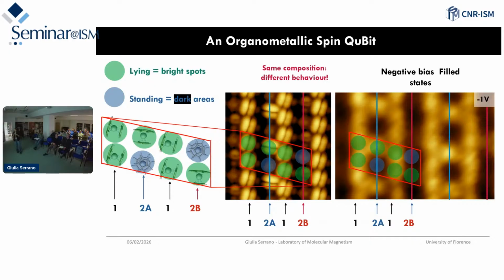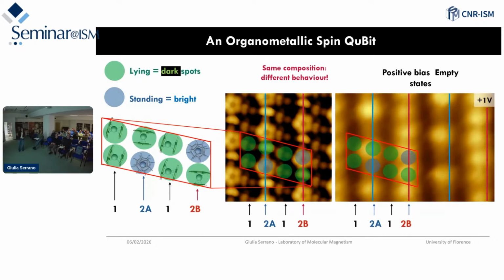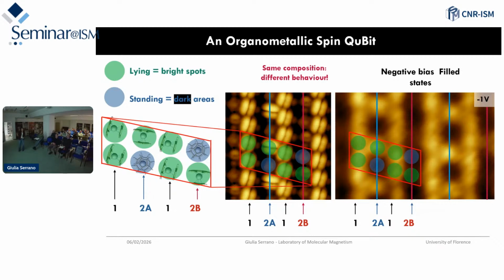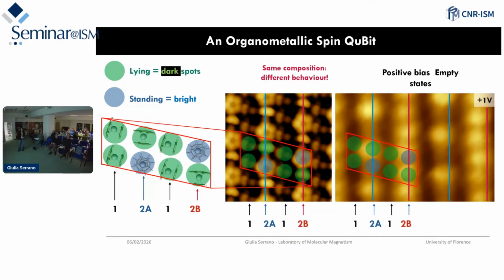So the rationalization of all of this came when we considered the packed layer. In the packed layer, we had a combination of standing, blue ones, and lying molecules, and we could rationalize this quite puzzling STM pattern by DFT simulation, and these are the real images, in which the pattern was actually rationalized by this quite complex cell. This was one out of 100 cells that the theorists attempted, and this cell could also rationalize the fact that we actually switch the molecules. So the lying molecules, for example, here appear as a bright spot in the STM, also in the simulated one, and then when you reverse the bias, you see them as a dark spot.